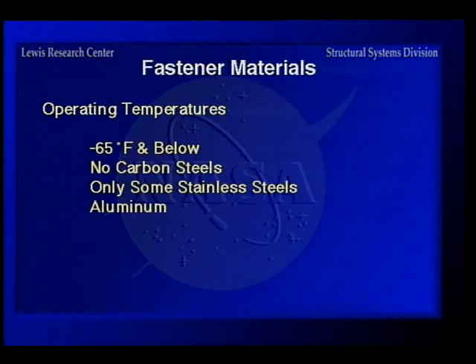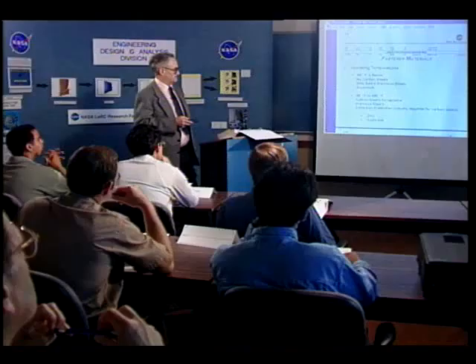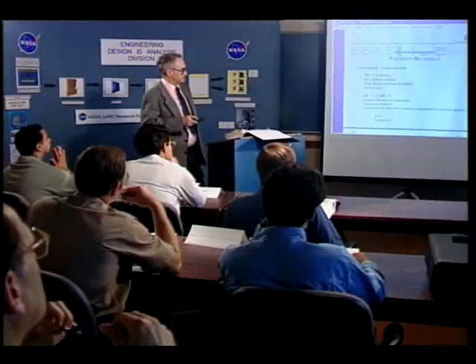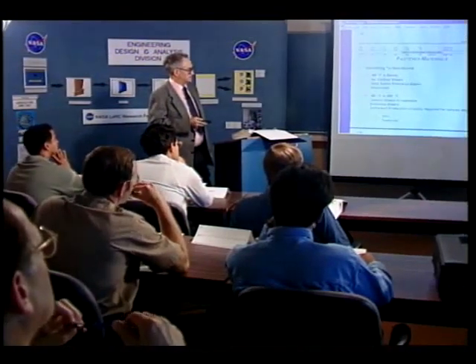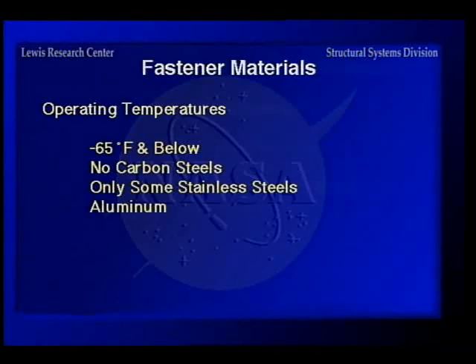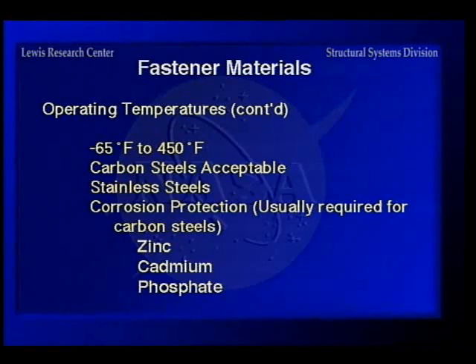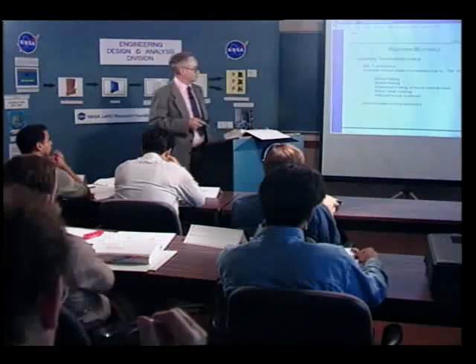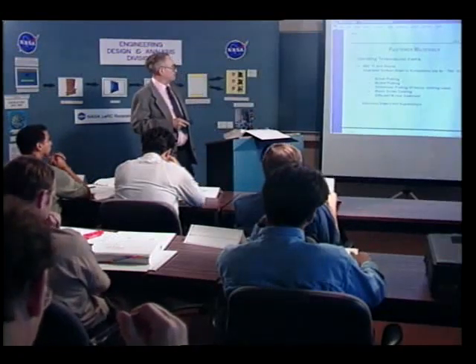Even some of the stainless steels won't go below about minus 150. Aluminum is good down to those temperatures. Then you go to the minus 65 to 450, which is an ordinary range for most engineering designs. Carbon steels are okay, and stainless steels are okay, but then you get into the business of needing corrosion protection for the carbon steel with the various types of plating like zinc or cadmium or phosphate or black oxide or whatever, and those will be covered, of course, later on in the platings and coatings section.